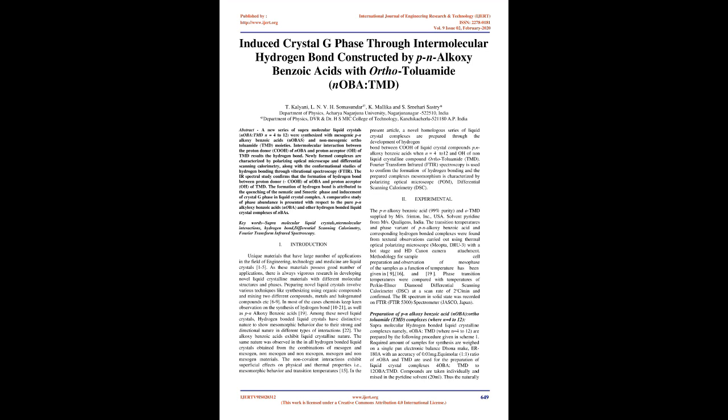The IR spectral study confirms the formation of hydrogen bond between proton donor, COOH, of nOBA and proton acceptor, O, of TMD. The formation of hydrogen bond is attributed to the quenching of the nematic and smectic phase and inducement of crystal G phase in liquid crystal complex.